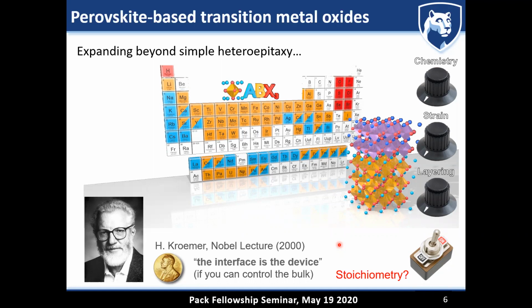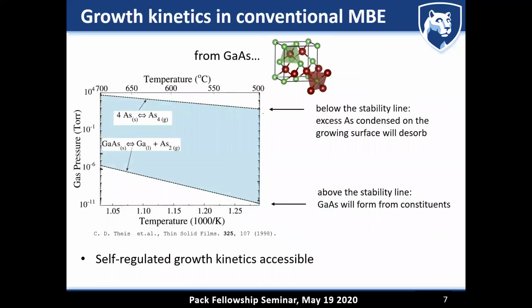So really the question always when you're growing these films and heterostructures, like your 101 homework that you have to address, is: can you even grow stoichiometric films? To give you a little bit of an idea of why this is so easy in conventional semiconductors, but so hard in oxides, I want to talk for a couple of minutes about the growth kinetics taking place in molecular beam epitaxy. In particular, I will use the example of gallium arsenide, which is probably the most grown material to date in a molecular beam epitaxy system.